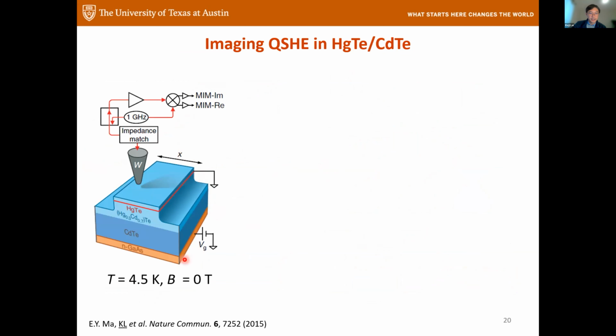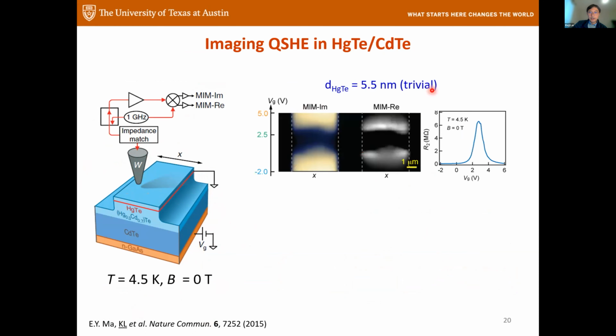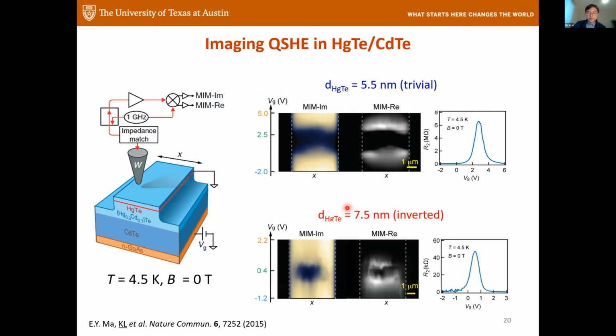And the experiment was done, again, not here at Austin, but at Stanford in my former postdoc lab. This is a tuning fork on top of mercury telluride. For the trivial states, to answer Fan's question, this is just a line scan. By changing the gate voltage, you see here the hole-like states, and this is the electron-like states. But in the middle, you can completely kill the edge states. Whereas in the topological one, the edges are always conductive. So that's an evidence of the topological features.